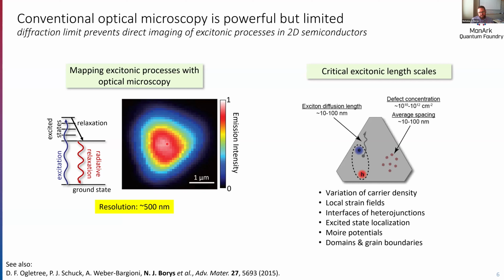And so this resolution limit doesn't really match the critical length scales of many processes in 2D materials. This is one of my common slides. It's oriented towards the physics in 2D semiconductors, but it applies also to all the other systems. The critical length scales of things like variations in carrier density, strain fields, interfaces, localization effects, and Moiré potentials, as well as domains and grain boundaries, are below this diffraction limit.